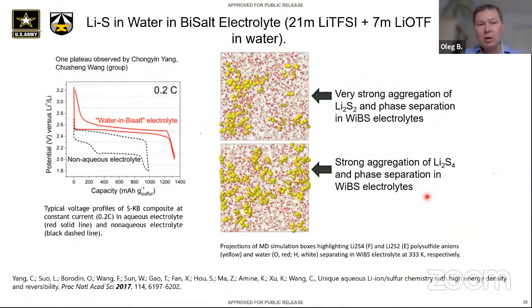And a somewhat similar picture was observed previously in Chongyin Yang's work from the Chusheng Wang group, where he used a bisalt water electrolyte, and there he observed one plateau. And also in this case, Li2S2 is essentially a very slow system, so I haven't completely equilibrated, but what I'm showing here is that they essentially got stuck one on top of each other and started phase separating. Li2S4 was much less so, but it was partially desolvated. So there seems to be a correlation between desolvation and pushing of Li2S4s together versus just segregation in one area,